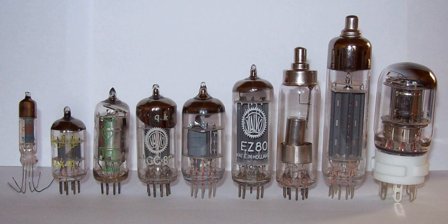It has been said that transmitters with vacuum tubes are better able to survive lightning strikes than transistor transmitters do. While it was commonly believed that at RF power levels above approximately 20 kilowatts, vacuum tubes were more efficient than solid-state circuits, this is no longer the case, especially in medium-wave AM broadcast service where solid-state transmitters at nearly all power levels have measurably higher efficiency. FM broadcast transmitters with solid-state power amplifiers up to approximately 15 kilowatts also show better overall power efficiency than tube-based power amplifiers.